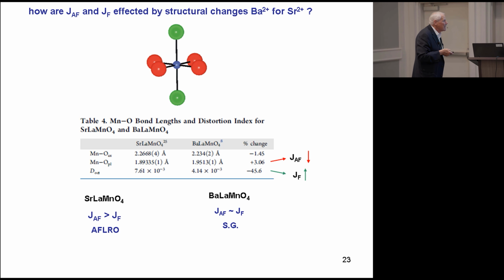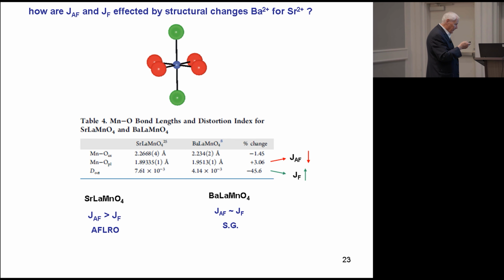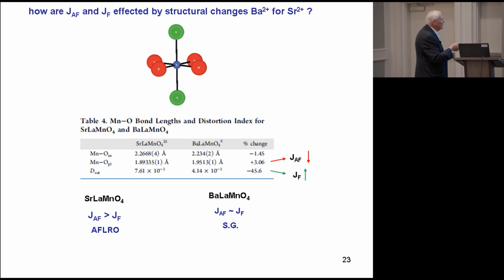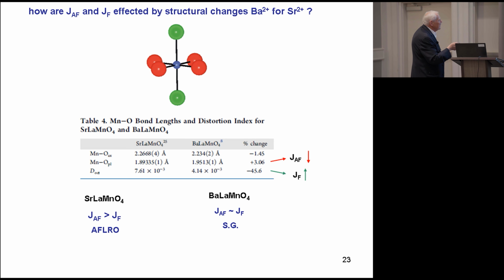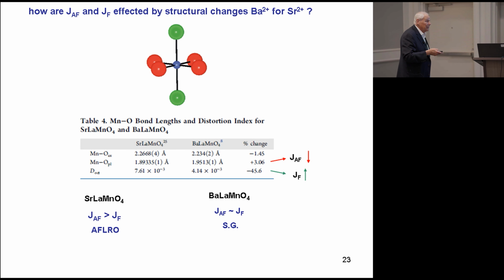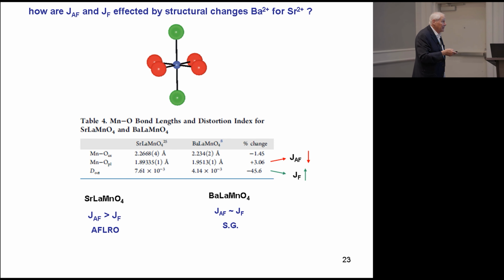Okay, so if we look at the manganese oxygen octahedron in the two materials, the thing that I'm going to point out is that you can define a distortion index here, and you can see that as you go from the all strontium phase to the all barium phase, the distortion index is significantly decreased. And a result of that is that the antiferromagnetic interaction will decrease and the ferromagnetic interaction will increase. And so it's possible that in this case, you have essentially compensating antiferromagnetic and ferromagnetic interactions. And this would kill off the in-plane correlations and you would get to a spin glass state.